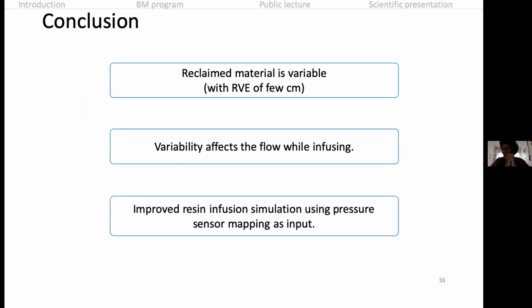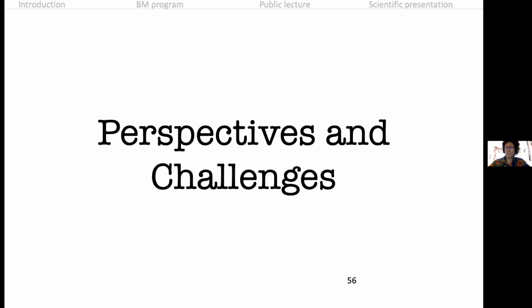Okay, I'm going to conclude on this scientific part. The main contribution of this scientific work was that we, of course, worked with this reclaimed material, and we showed that it was variable. The variability was shown to affect the flow while we were infusing, so we have to control this variability to be sure that we don't have defects and trapped air, for instance, at the end. And we also developed a simulation of the infusion that enables us to predict what's happening during the infusion.